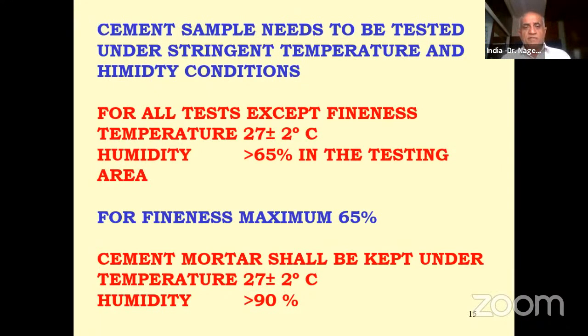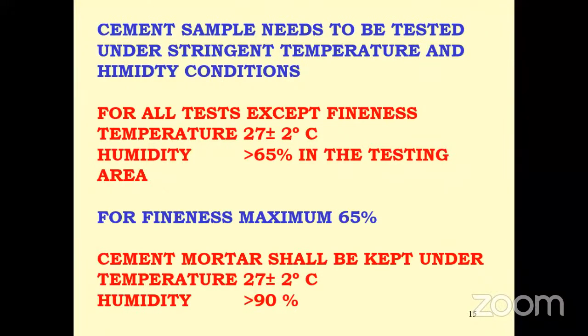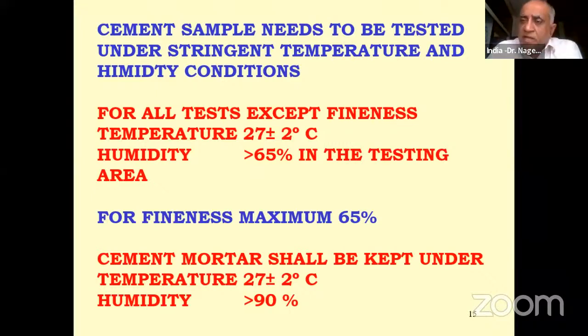For all tests except fineness, the temperature in the cement laboratory should be 27 plus or minus 2 degrees Celsius always. The cement testing room should have very stringent temperature and humidity arrangements. Humidity control and temperature control should be there. So humidity in the cement testing room should be more than 65% in the testing area. Suppose you want to find out the fineness of cement using the Blaine apparatus, the area wherever you are conducting the test, the maximum humidity shall be 65%. It should not cross 65%.